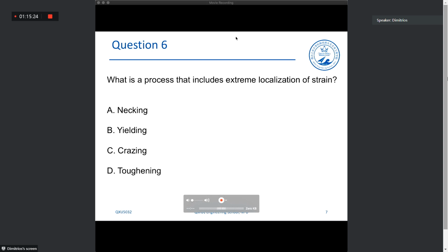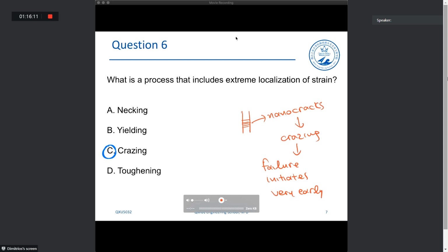So extreme localization of strain takes place in crazing. Necking is not as highly concentrated strain localization. Okay. Because the strain is distributed along the neck, while in crazing, the strain is essentially localized in these nanoscale regions, nanocracks, as a result of crazing, and failure is initiated very early.